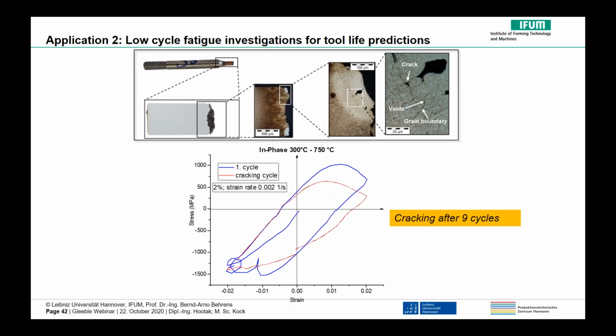In contrast, no oxide intrusions formed in the in-phase TMF case. Here, most of the damage occurs in the form of internal intergranular cracking at the grain boundaries. Micropores are visible at the grain boundaries, which lead to the formation of macropores in adjacent areas and eventually crack initiation. The main damage mechanism is creep because tensile stresses coincide with high temperatures promoting void growth. The performance of the above-mentioned LCF and TMF tests confirm the findings of the studies in literature, and the cracking occurred already after 9 cycles.